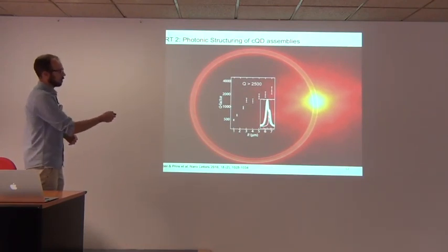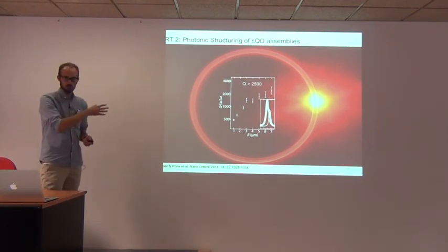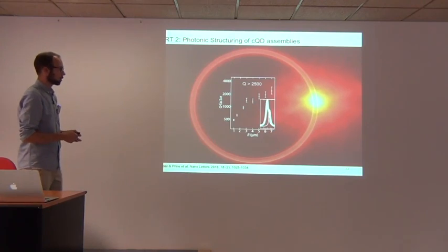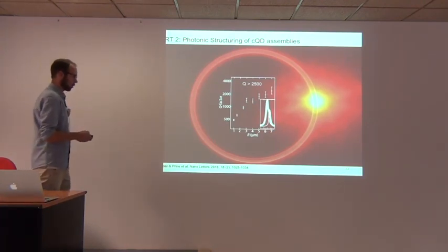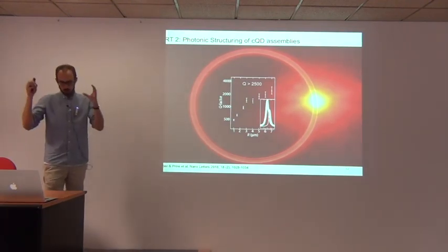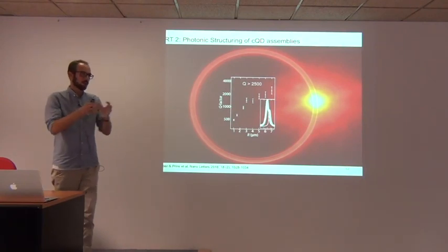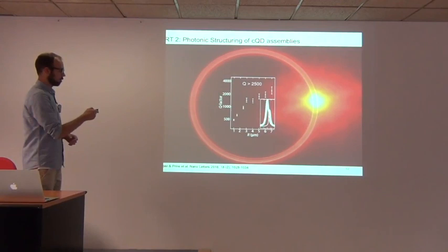interference peaks with quality factors up to 2500, which for quantum dot resonators is one of the highest reported. And of course, this is proportional to the radius of the system. What we're really interested in is lasing. So now instead of focusing the laser down on one edge, we just carpet illuminate the ring laser.